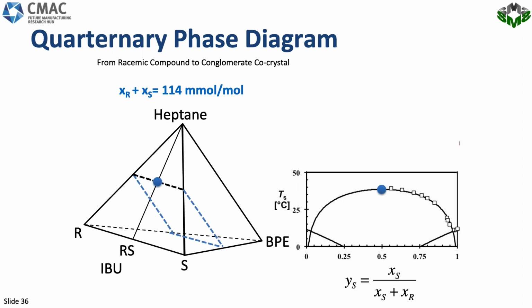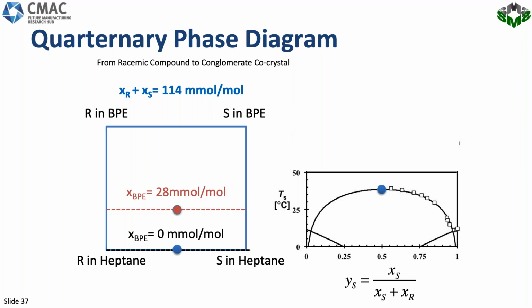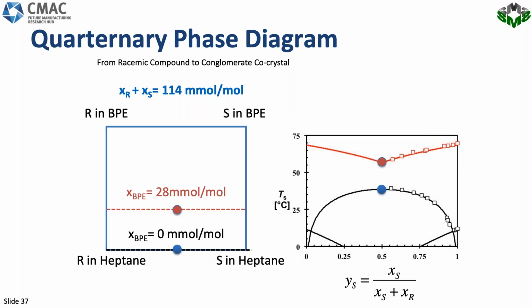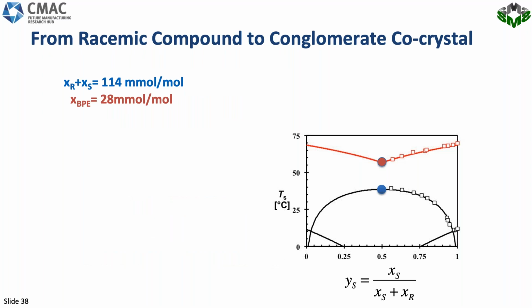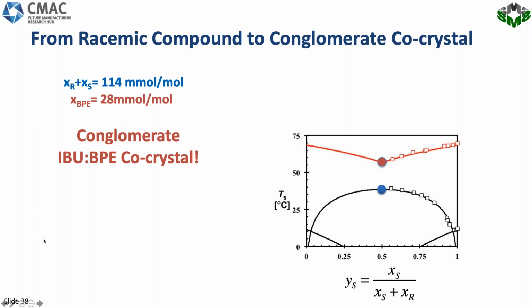Now we can add a little bit of coformer in the background, and we chose to add 28 millimoles per mole of BPE. If we measure the clear points, we see the red points appearing. These red points show a V-type profile, and that is very characteristic for a conglomerate system. So by adding this compound BPE in the background of the solutions, we form a conglomerate co-crystal system. We have a conglomerate ibuprofen BPE co-crystal, and that can serve as the basis for a chiral separation process design.